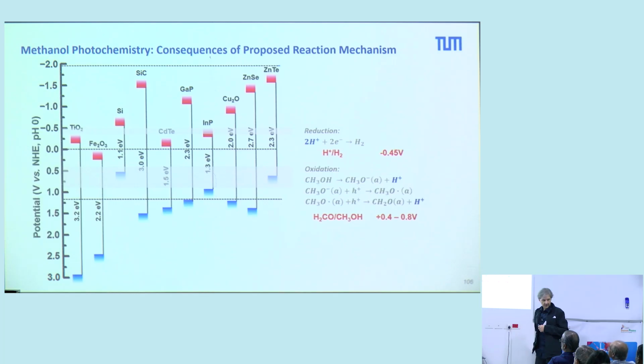Now, why is this important? We have shown that this mechanism I introduced in the very beginning has some restrictions on the semiconductors. That means you have a band gap. You see here different semiconductors with different band gaps, the valence band and conduction band, the upper edge and the lower edge. And I told you that you have to design the band gap in such a way that the oxidation potentials lie in between the band gap. So there are very strong restrictions on the use of the semiconductors, because you not only have to align the oxidation potential, but also the reduction potential.